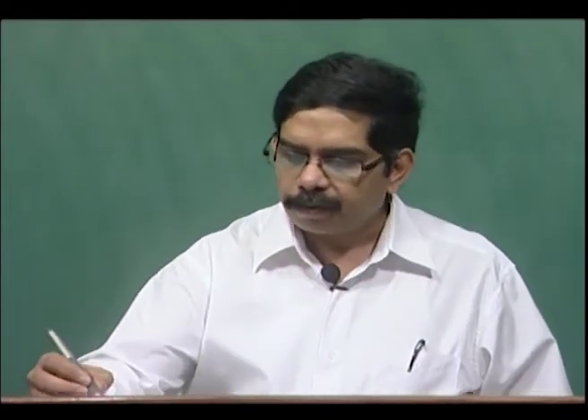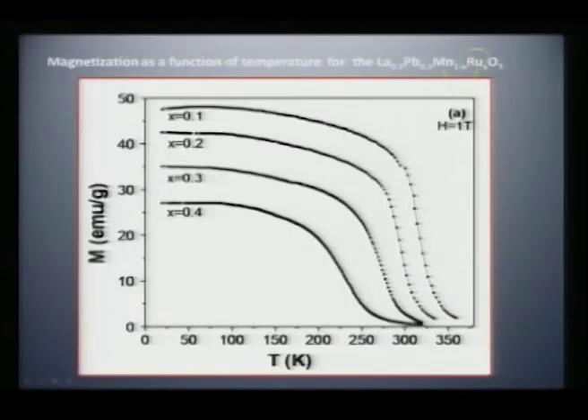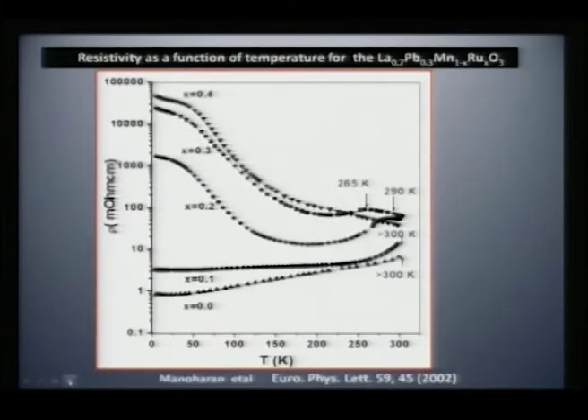show you. Suppose I substitute ruthenium in the manganite, then keeping lead concentration constant, as a function of ruthenium concentration you still see a very strong ferromagnetic loop. In other words, even up to 40%, I am seeing almost for every ruthenium there is a nearest neighbor manganese in such a unit cell, you would see a strong ferromagnetic transition happening. So what is it that makes it important?